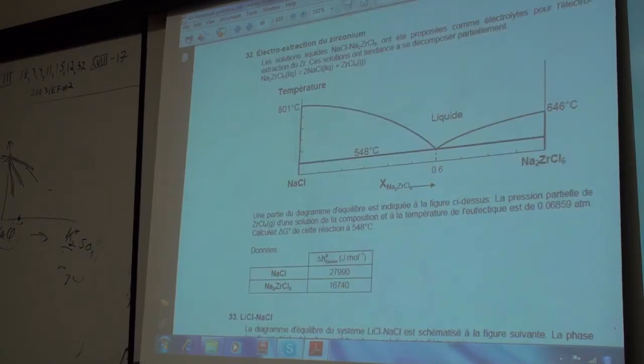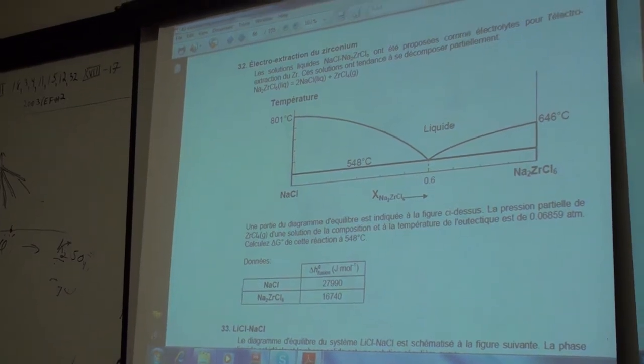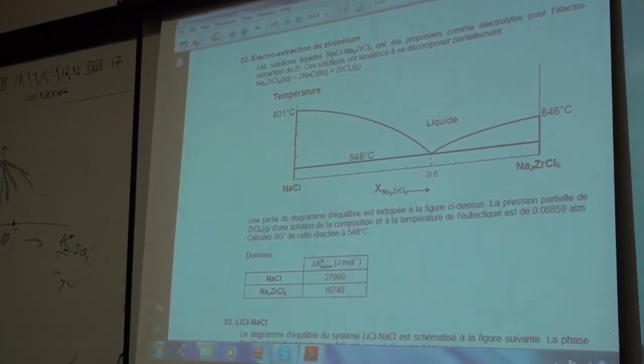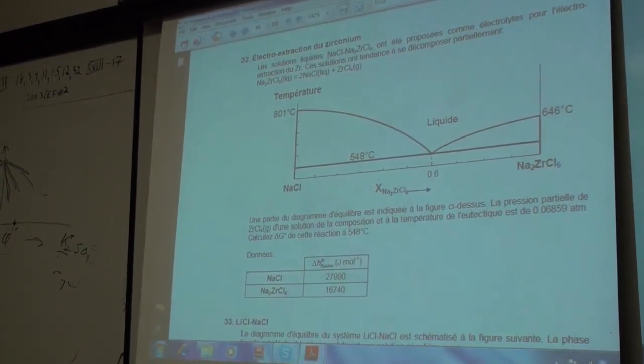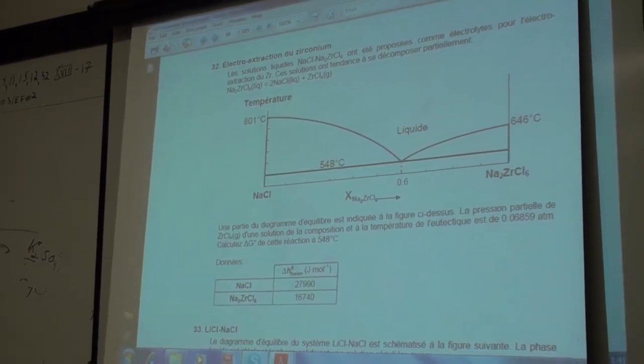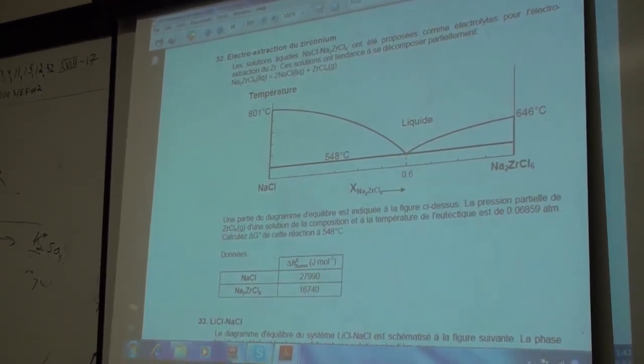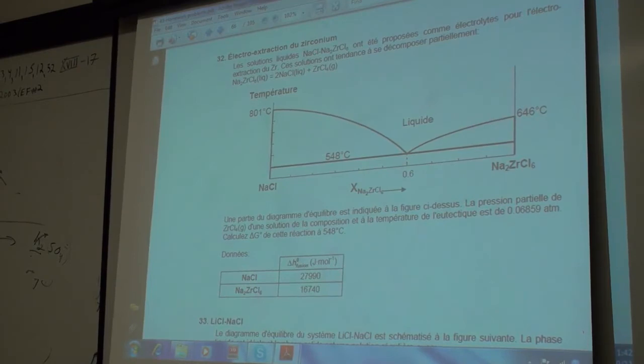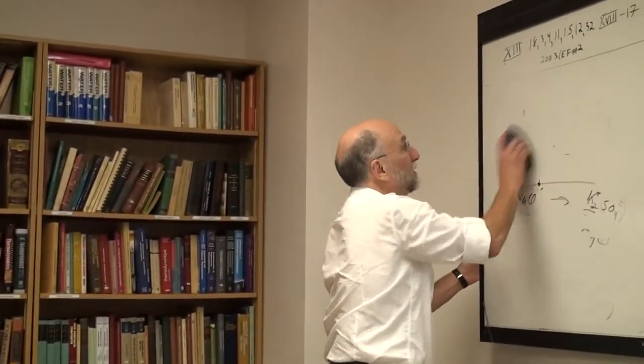Okay, here you have your sodium chloride, sodium hexachlorozirconate solution. They've been proposed as electrolytes for electrolyzing zirconium. They do work, but you end up getting a dendritic deposit rather than a nice flat one. But the solutions partially decompose, so if you take your sodium chloride, sodium hexachlorozirconate solution, and above it you'll have a gas phase, and the gas phase will have a ZrCl4 gas in it at equilibrium.